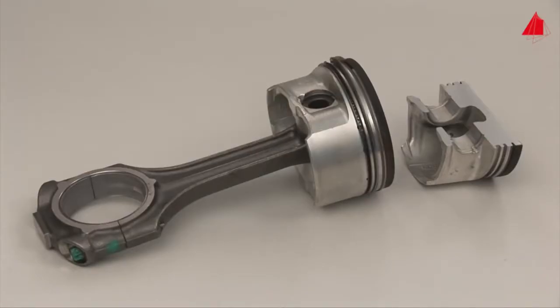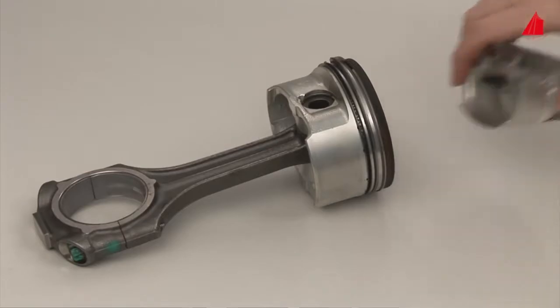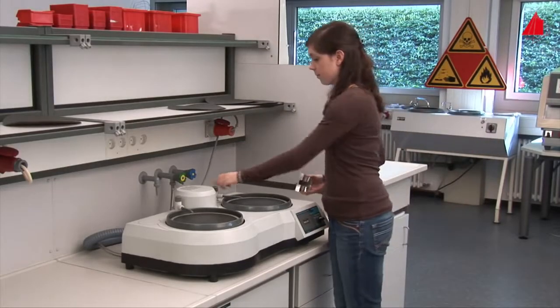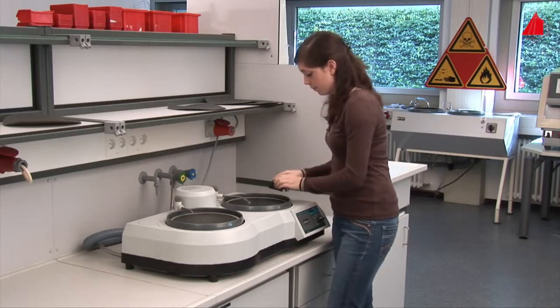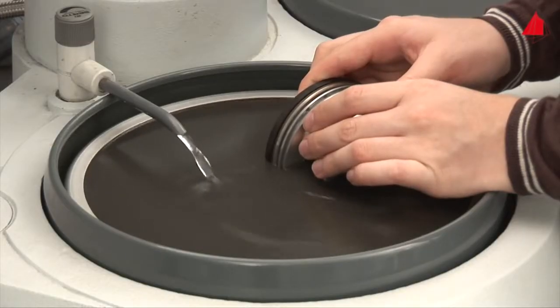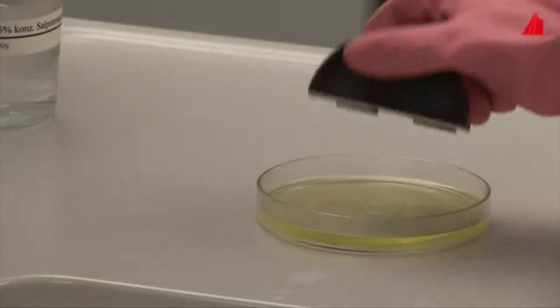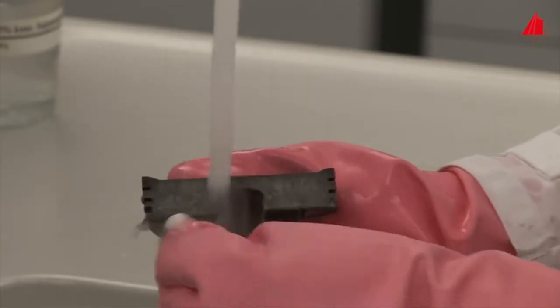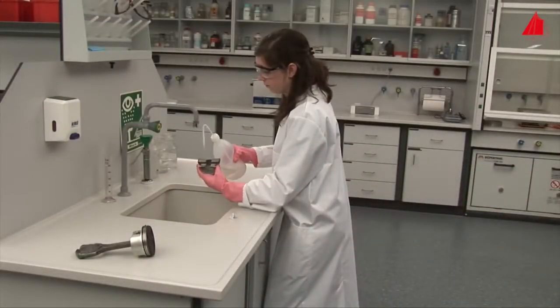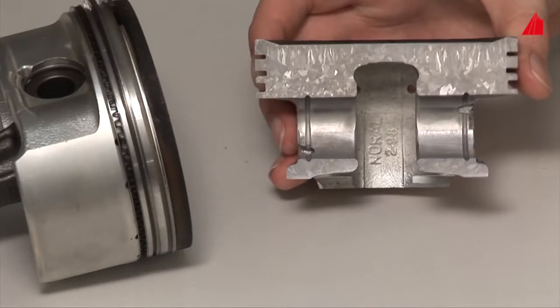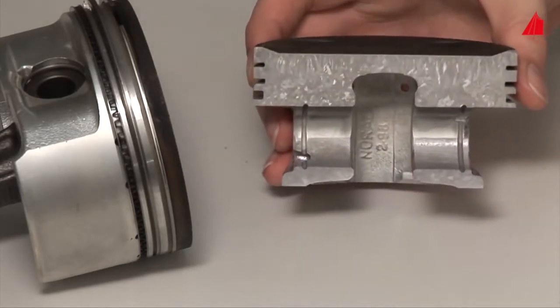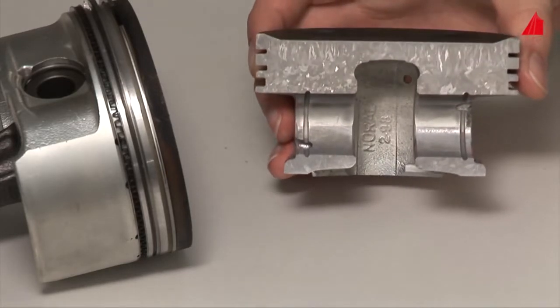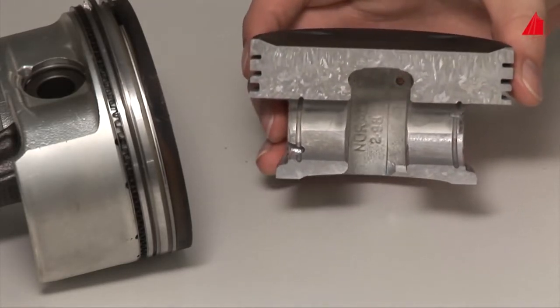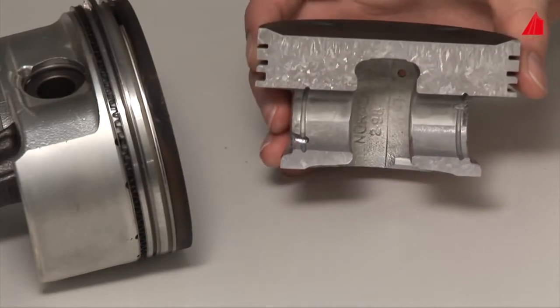As a second sample, the material tester examines a piston from a petrol engine of a passenger car. The procedure is the same as before. Careful sectioning under liquid cooling is followed by wet grinding with coarse-grained paper, then wet grinding with medium-grained paper, and finally the decisive step, the etching. After washing, cleaning and drying, fantastic crystals are visible again. It should not be concealed that these crystals, these grains, are not perfect and uniformly structured crystals, but so-called primary grains. Within the primary grains, many other very small crystals and also crystal defects may be found, but these can only be seen with appropriate microscopes.